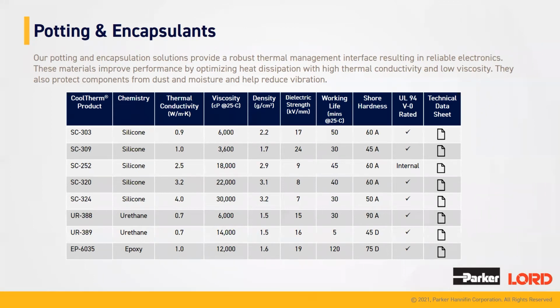And if you go through, for instance, thermal conductivity, you see that you have an offering going from 0.7 up to 4, and even for 4, like the SC-324, you see that even for 4 watts per meter Kelvin, you still have a quite decent viscosity, which is around 30,000. And as I said, you have different hardnesses. You have soft materials in the Shore A range, going up to the Shore D range for much harder material, again, depending on the requirements that you have.